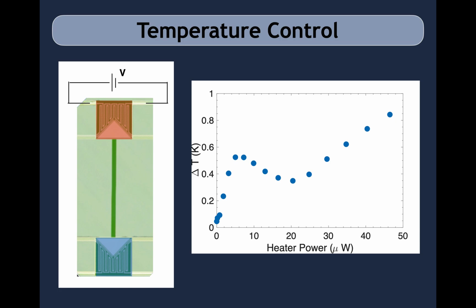The plot on the right shows the change in temperature as a function of applied heater power across a bulk silicon substrate at 10 millikelvin. Since the silicon nitride bridge is both a thin film and suspended, we can expect a delta T greater than what is plotted here.